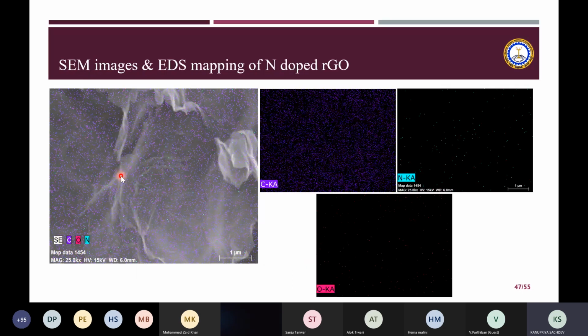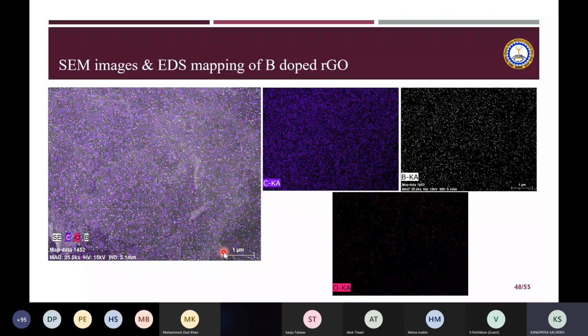And this shows you the SEM image and the EDS mapping of the nitrogen doped RGO. These are the different elements, and this represents the distribution of nitrogen. This is your carbon, this is the nitrogen, this is the elemental mapping which we get from the EDS, which is added to the scanning electron microscope, and this is the presence of oxygen there. You can see that there is an almost uniform distribution of nitrogen in the sample. This is the EDS mapping and SEM image of boron doped RGO, and this is the presence of boron in the sample.